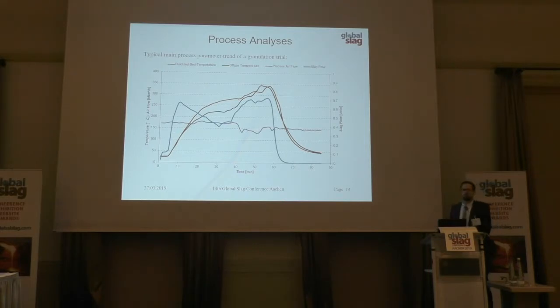The orange and black lines show the temperature of the granulate bed and the off-gas temperature. You can see you're starting the process cold. You need a certain time of 10 to 15 minutes to heat this process up. What we have done here, for example, in this trial, is reduce the airflow after 40 minutes of operation to increase the off-gas temperature and the fluidized bed temperature, to maximize the off-gas temperature for heat recovery application.